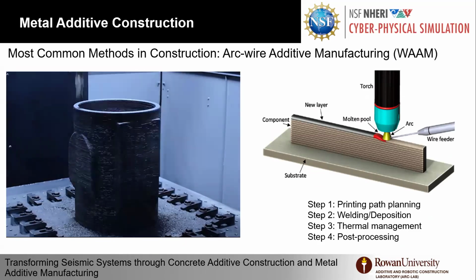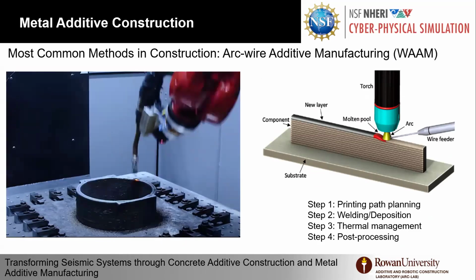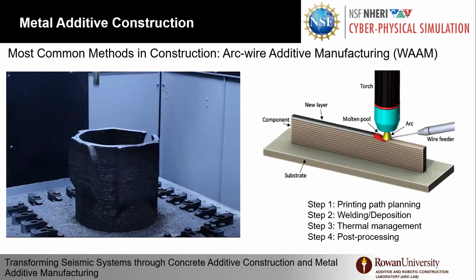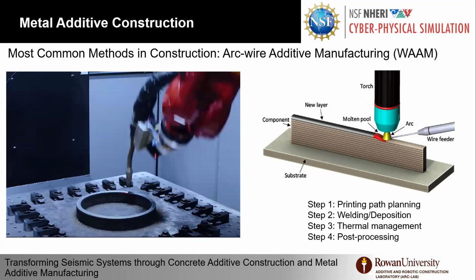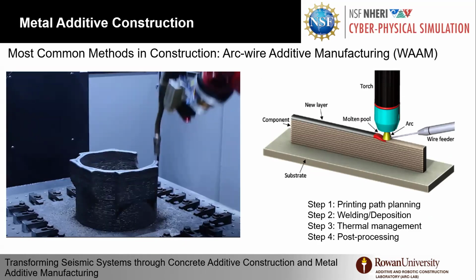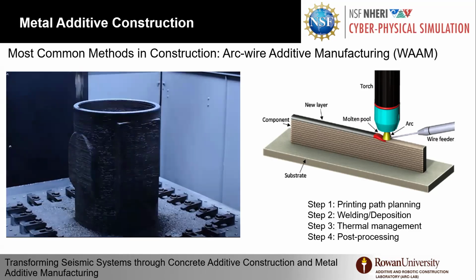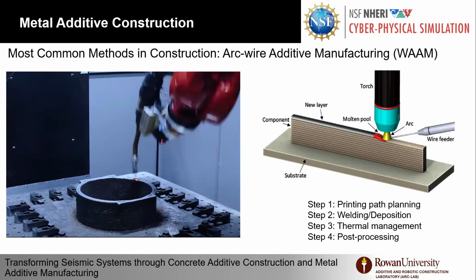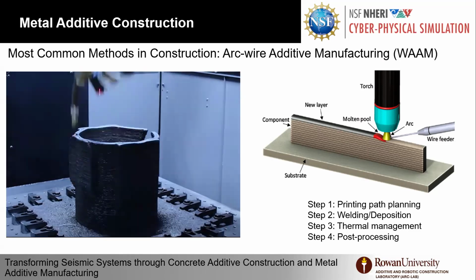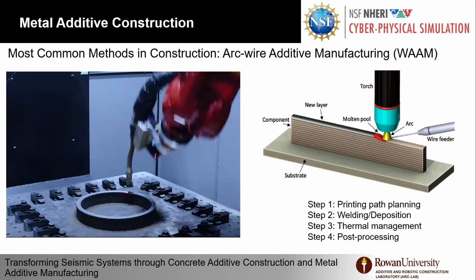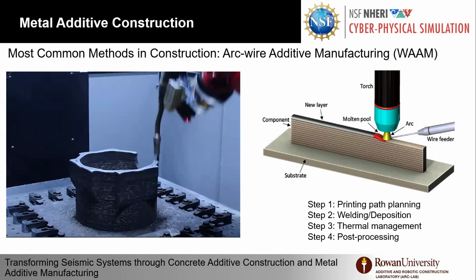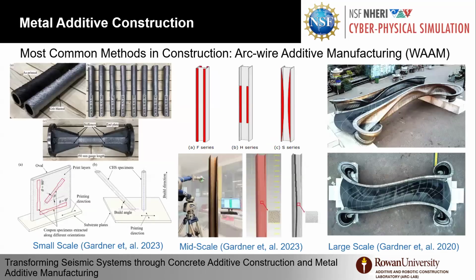We need to prepare the path for printing, deposition, and welding. You have to do a lot of thermal management and post-processing. As you can see here, you can see a lot of layers. And now we can have a fatigue issue. We can also have a corrosion issue. And we also have the steel now as a kind of anisotropic material.